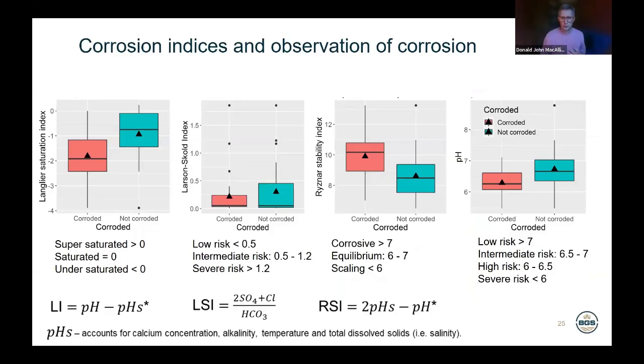We then looked at some of the corrosion indicators that are used quite widely, and at how the values of those indicators that we calculated related to our actual observed corrosion. There are four indicators here: the Langelier saturation index, which accounts for calcium concentration, alkalinity, temperature, and total dissolved solids, so the salinity level. The Larson-Skold index, which accounts for sulfate and chloride. The Ryznar stability index, which is a variation of the Langelier index. And then the pH less than 6.5 threshold.